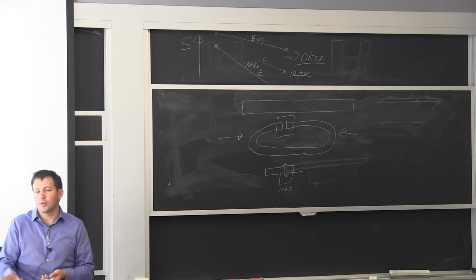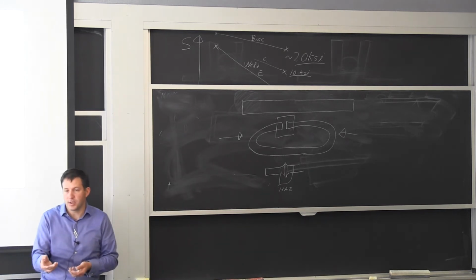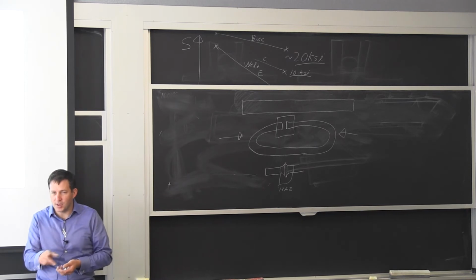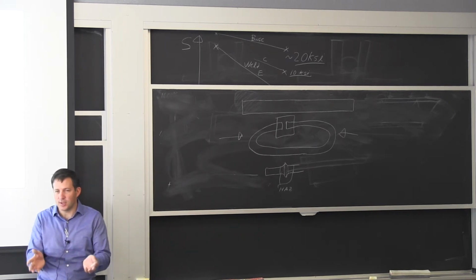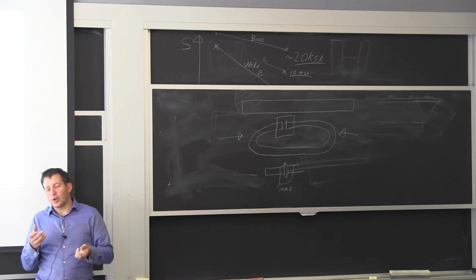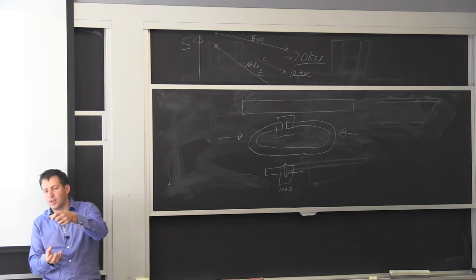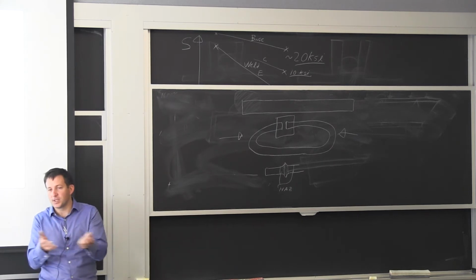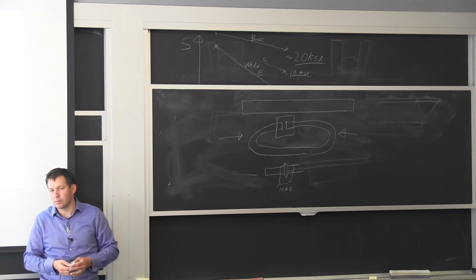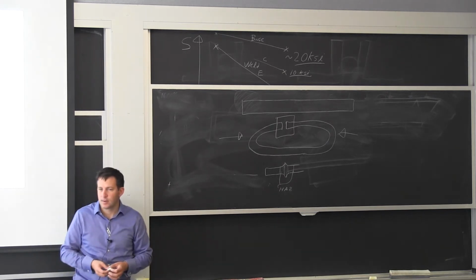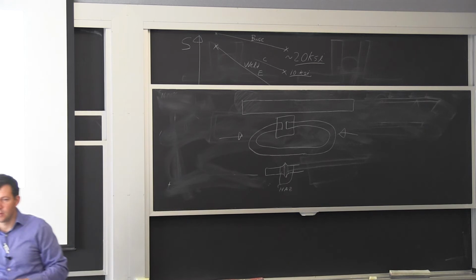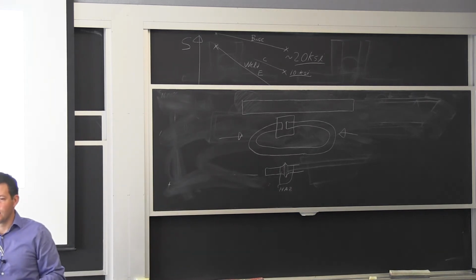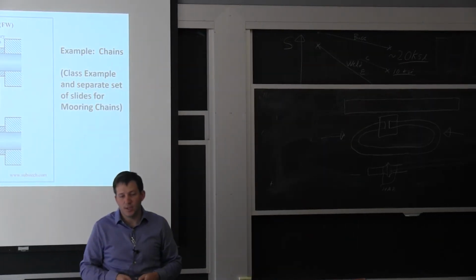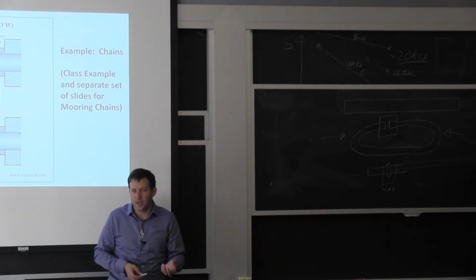Because the problem of distortion in machining is when you have these residual stresses and you machine them away, so you take away the tension zone, and then all of a sudden it's deflecting on you. When it's a complete assembly, it's not a whole lot of distortion, because you've got a zone of tension next to a zone in compression, and they essentially just reduce in magnitude. So do you often have cases where people will be welding materials that they did not stress relieve, and the whole structure just ends up warped? Oh yeah. And then the question is, is that deflection acceptable or not?